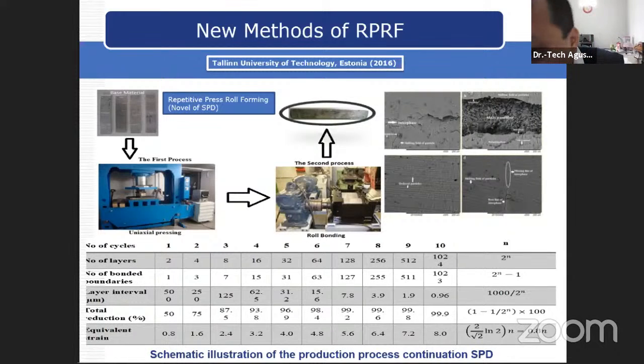So the first uniaxial pressing was carried out without lubrication, same as ARB, using approximately, if we use composite material, a 50 ton hydraulic press, and then reduction same as ARB, 15%. And during the second step, second cycle, the reduction by rolling was performed with the strip preheated as well to improve formability. Because for aluminum series 7, it's very difficult to press. So we add heat treatment annealing. This process is capable of reducing 1 till 5 millimeter, I mean, and I have finished trials for RPRF material with composite aluminum series 1 till series 7 and use ceramic silicon carbide and aluminum nanofiber as well.